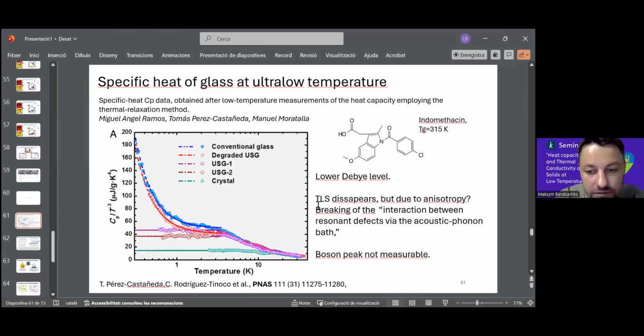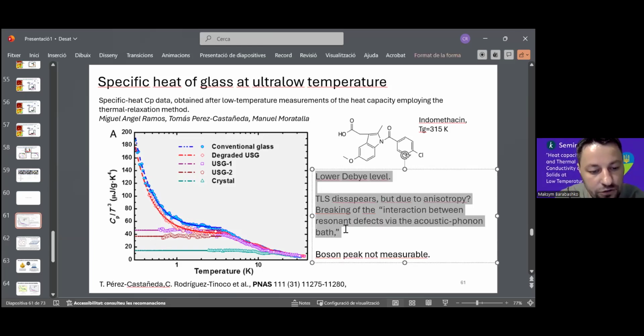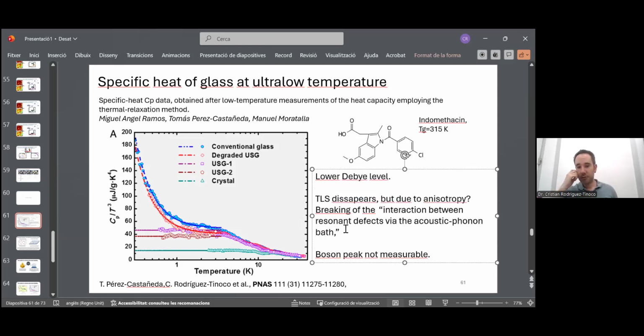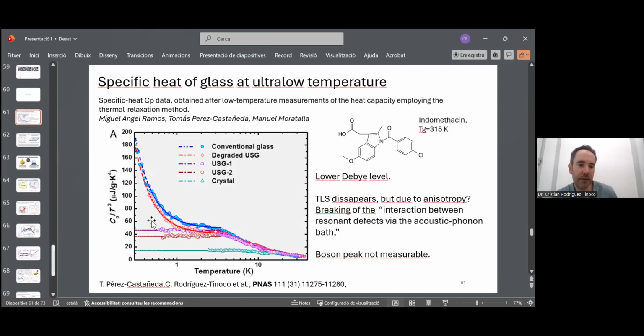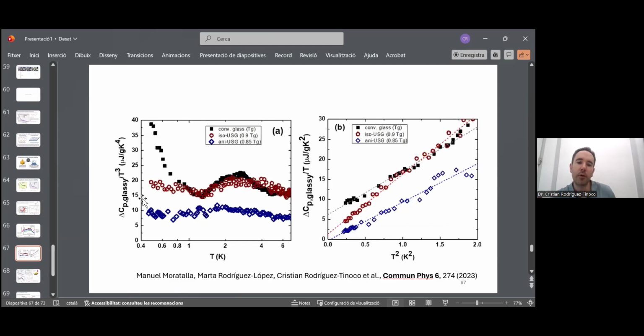Your opinion, is it reasonable to find some correlations between the temperature of glass transition and the effects that you observe in the decrease of the boson peak? Well, we tested so far two materials. Indomethacin, which is this one, 315, and we also tested the TPD, which is the other one, which has a Tg of 333. And in both cases, we see the same. So we see a suppression of the TLS in the ultrastable state.